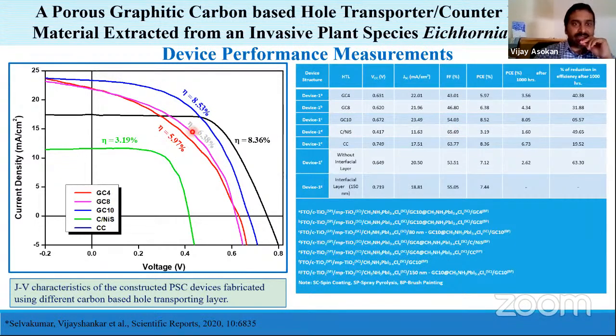Then finally, this layout is showing only the combinations of different annealing temperatures to show how those annealing temperatures influence the efficiencies. For example, here, with a 1000-degree annealing temperature, we have improved the efficiency to 8.53 compared to other annealing temperatures and other carbon and carbon nickel sulfide, which we showed in our previous report. So this is one of our recent research.